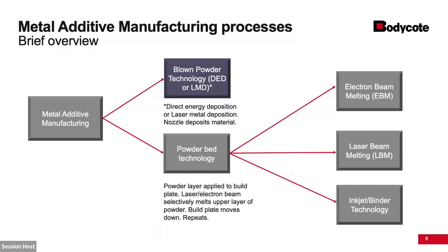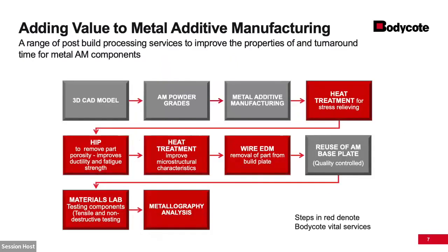So the value add portion: how do you get from the CAD design to an airplane? You've got your CAD model, you've got your powders, grades, then you build your plate, then the value add comes in your heat treatment. Your first step is going to be a stress relieve. Then you'll roll it into a HIP for hot isostatic pressing, which will get rid of the porosity. Heat treatment to improve the microstructural properties. You wire EDM the part off the build plate. The build plates are reusable. Do material lab, metallurgical analysis, and your parts are generally good to go on an aircraft.